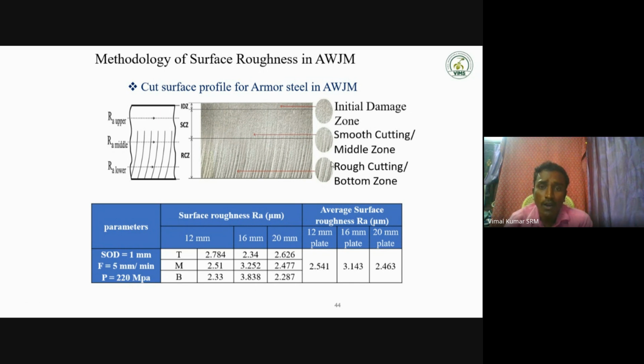Afterwards, it depends on how far it penetrates in depth. So the top cut surface and bottom cut surface are not equal, because water traces are formed on the cut surface. We can easily identify it in this picture. So we can measure the top, middle, and bottom surface roughness for 3 different thicknesses. Here T is the top surface roughness, M is the middle, and B is the bottom. These are the values for the 12 mm, 16 mm, and 20 mm plates.